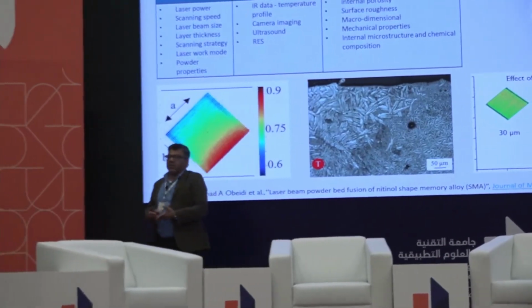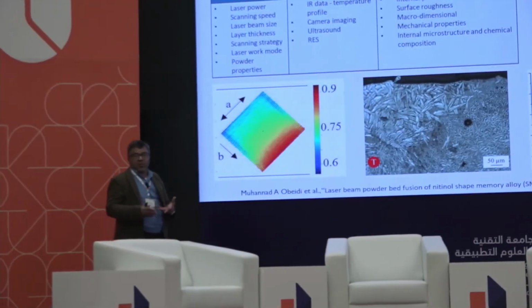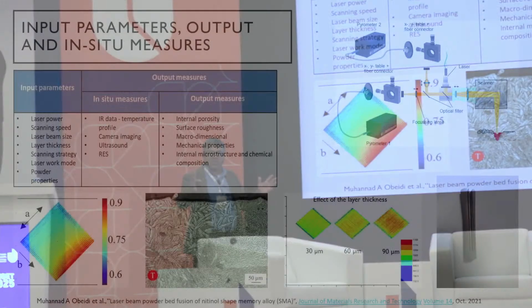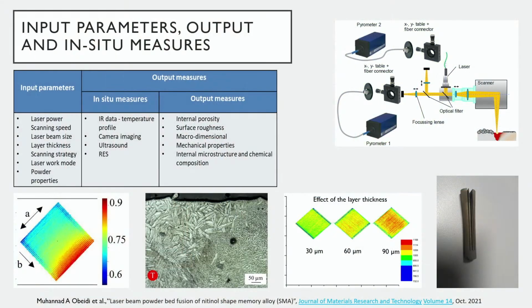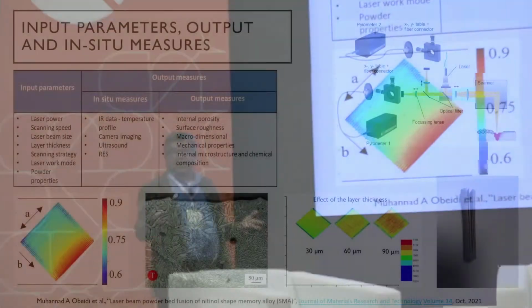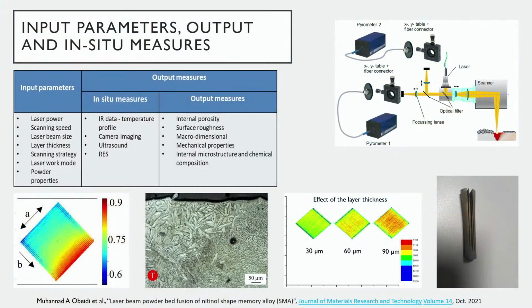The post-process for that is called HIP, hot isostatic press, in which we put the part in a high pressure chamber, apply high gas pressure, like more than 700 or 800 bars, with high temperature. And that reduces the internal porosity inside the part.